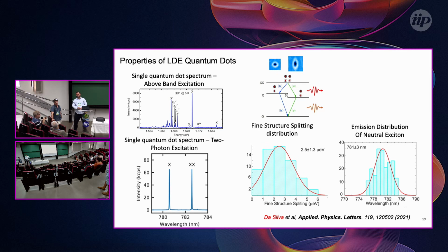No, what I'm saying is, if you try to excite gallium arsenide below the band gap, in the middle of the band gap, you have to create a virtual state. No, the aluminum gallium arsenide band gap, not the gallium arsenide band gap. Yeah, but not two-photon absorption.